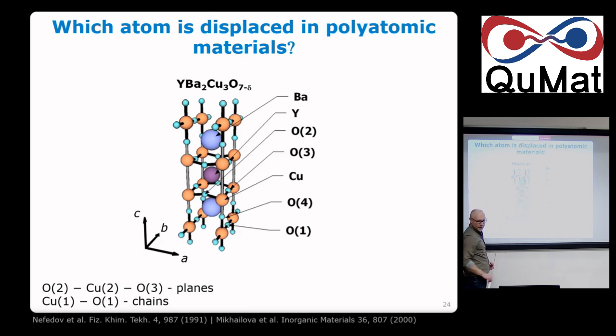So people knew already that when you change oxygen, it's going to be from here. When you change that, you change the properties of the material. And the rich thing about that is that this material can go from insulator to superconductor to metal, bad metal, antiferromagnet, just by changing the oxygen. So we say, okay, that's the knob you have to change the properties of the material.